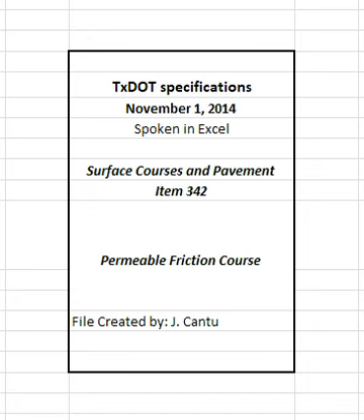Take corrective action and receive approval to proceed after any production suspension for non-compliance to the specification. Submit a new mix design and perform a new trial batch when the asphalt binder content of any wrap stockpile used in the mix is more than 0.5% higher than the value shown on the mixture design report, or RAS stockpile used in the mix is more than 2% higher than the value shown on the mixture design report.